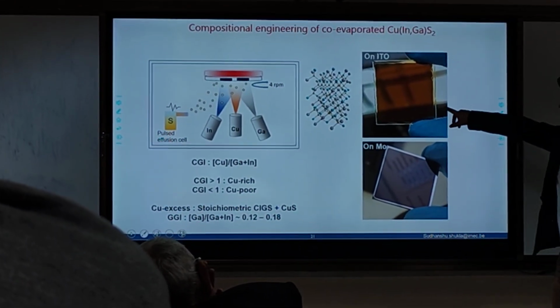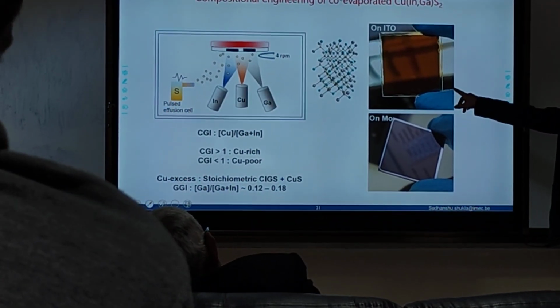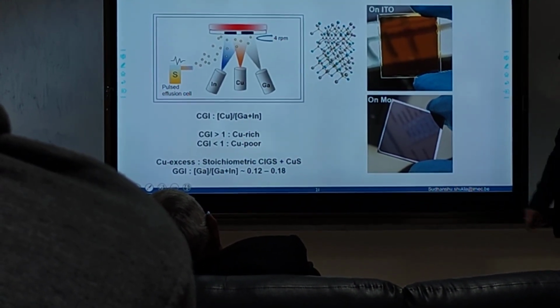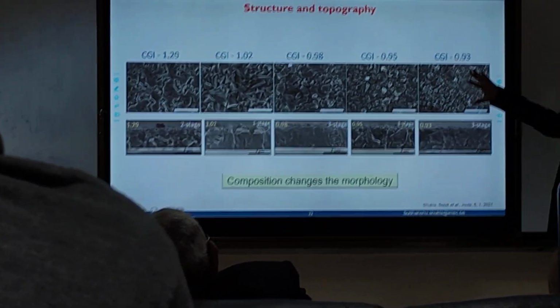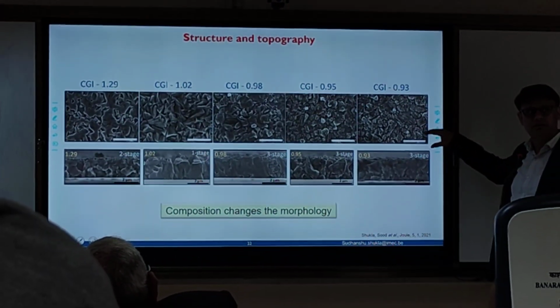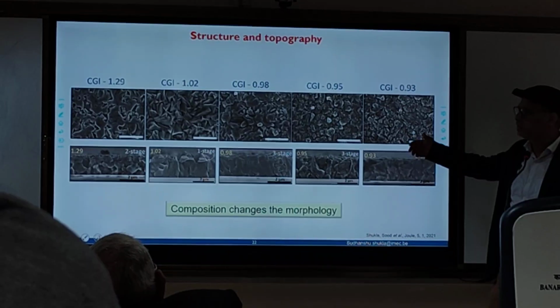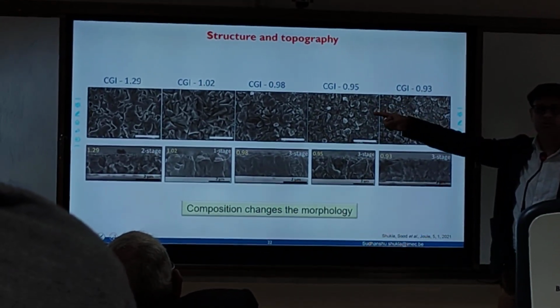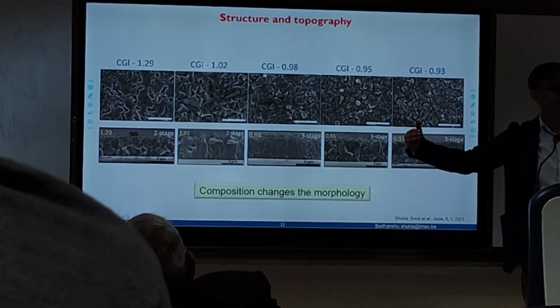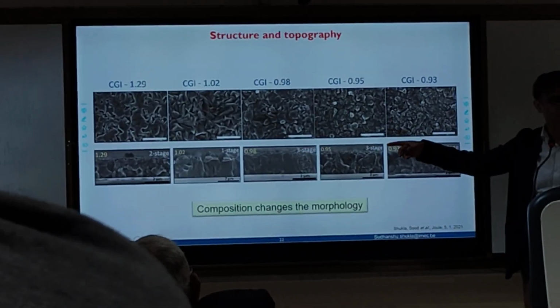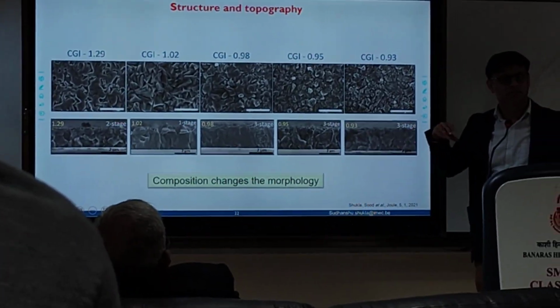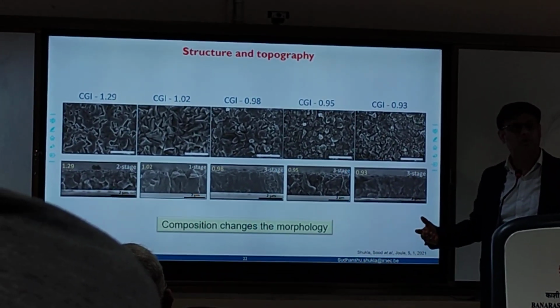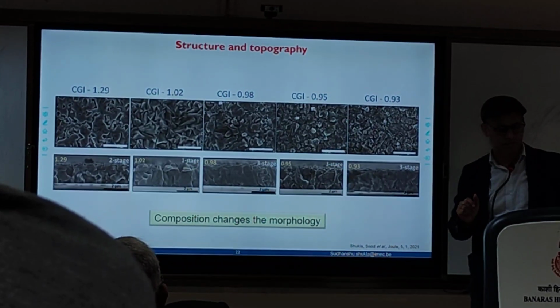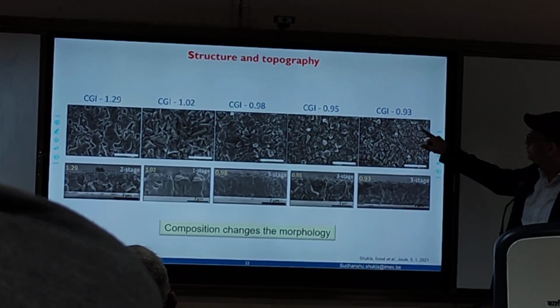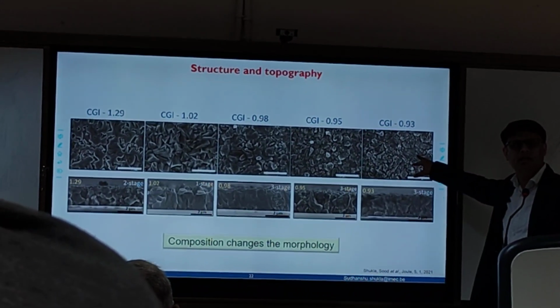differently. You can also make this semi-transparent, so they are very cool for semi-transparent solar cells. These are on molybdenum. As you can see, these numbers indicate how low you go in terms of CGI, so how copper deficient your films are. So that's a CGI of 1.29, so the films are highly copper rich. And you see the morphologies are very different. So composition also decides the morphology. It's also one parameter that you can tune. So I went from 1.29 to very copper deficient, 0.9.